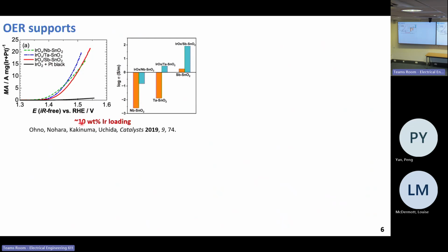So it's possible to further reduce iridium loading to around 10%. However, these doped tin oxides are still less conductive than iridium oxide, because the conductivity has been improved a lot when mixed with iridium oxide, and there's no clear trend in the activity of the water oxidation.